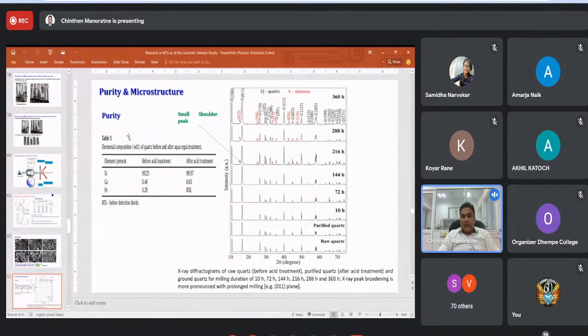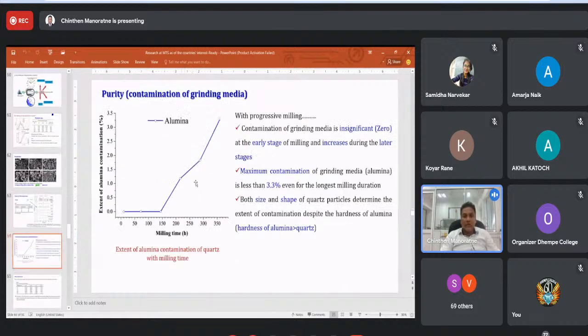Now, when you look at the XRD, you can see up to 260 hours of ball milling, there is no contamination due to these balls. Now, we use alumina balls in this ball milling, but after 260 hours of ball milling, you can see alumina contamination, but it is very negligible, a very low amount of contamination. You can see this very small hump appearing near the quartz peak. It can't even be distinguished. Very small amount. And this is the normal composition of quartz used in our study. And this shows that after 260, some level of alumina contamination can be observed, but it is very low, less than 3.3.